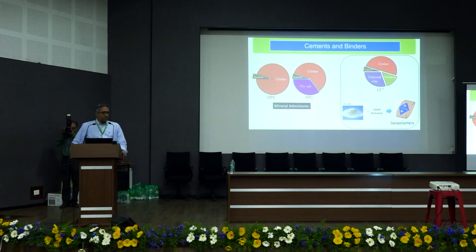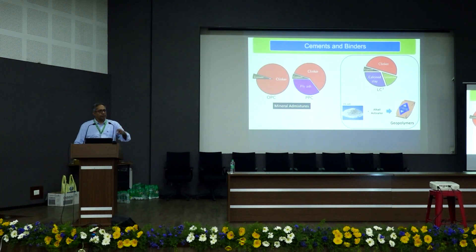There are newer binders coming into the market, all with promising potential. LC3, which is calcined clay, operates at a clinker factor of around 50%. There's also a whole set of new binders broadly called alkali-activated materials — the term geopolymers is misused in that context. Depending on the source, you could end up with a geopolymer or with calcium aluminosilicate hydrate, which is basically CSH with aluminum substitution. This is the broad spectrum of binders available to us, and within alkali-activated materials, the choices are growing by the minute.